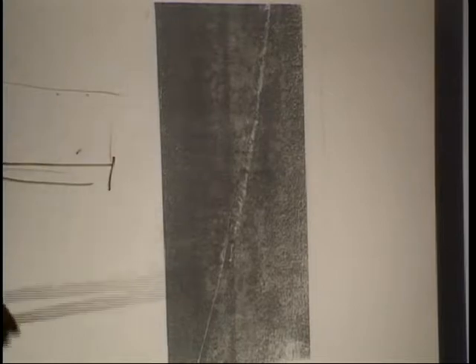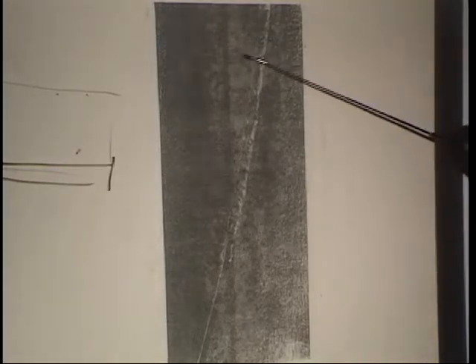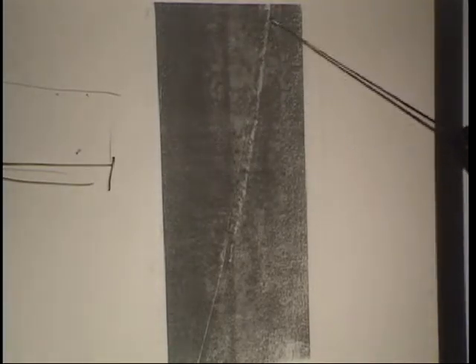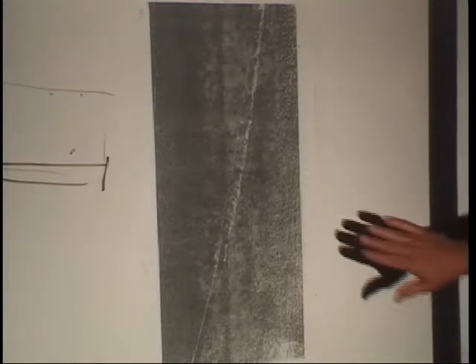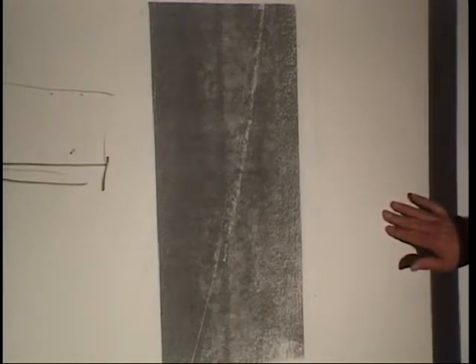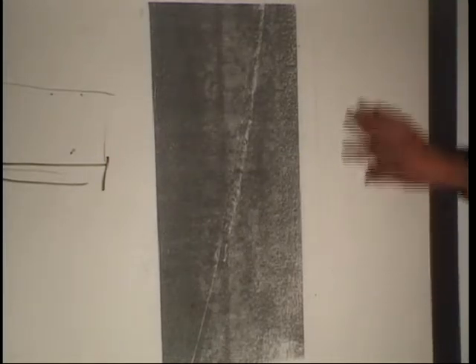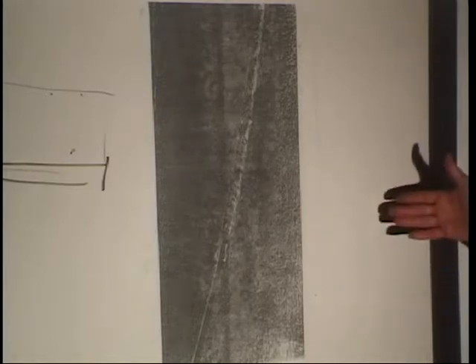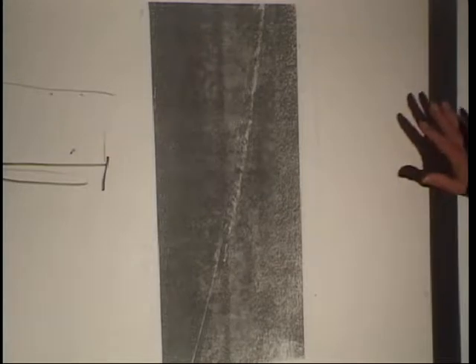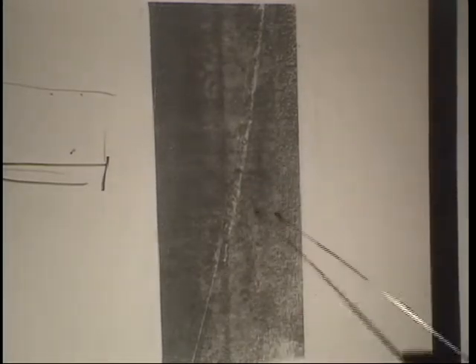And this is the inside of a large diameter pressure vessel, but it's not very thick. And what this picture shows is a root bead done with MIG and how it's fused into the sides. And in your picture, you can just barely see some of that glossy black stuff on here, which is silicate. And you're going to get that on both the inside and the outside of that. But on the outside it is going to really be humped up like this as you put that root bead in, and then you're going to have to grind that down to clean white metal in order for you to deposit your next pass. But we don't care about that. This is what we care about. This is the important thing, that it's breaking everything down.